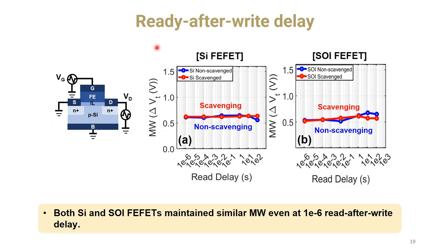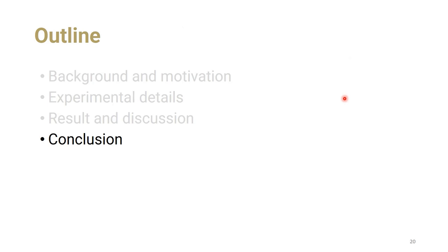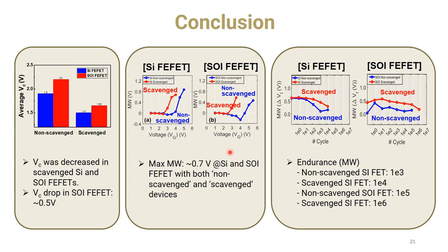And also, we measured read after write delay. For both silicon FET and SOI FET, from 100 seconds to 1 microsecond, the memory window is pretty consistent. So even at the very fast 1 microsecond read delay, we can see the memory window for both silicon and SOI FEFETs. So, conclusion.